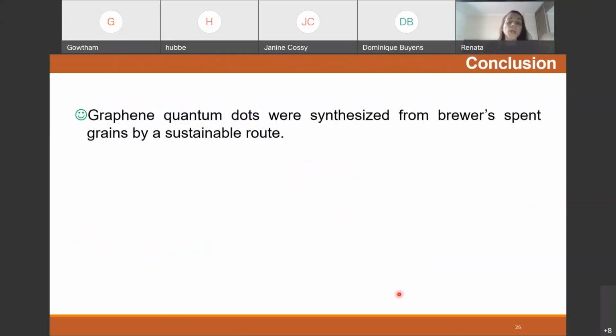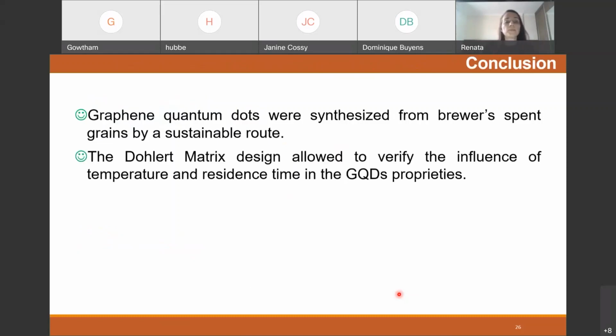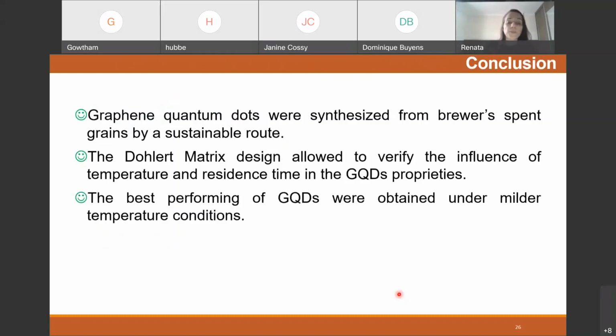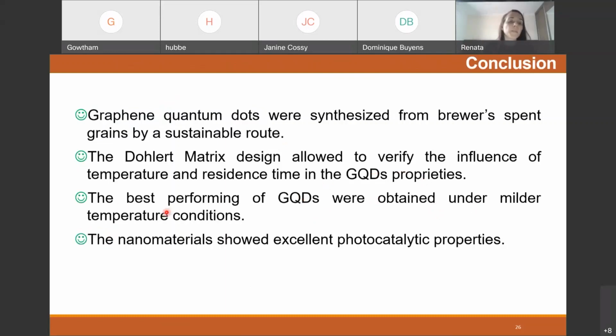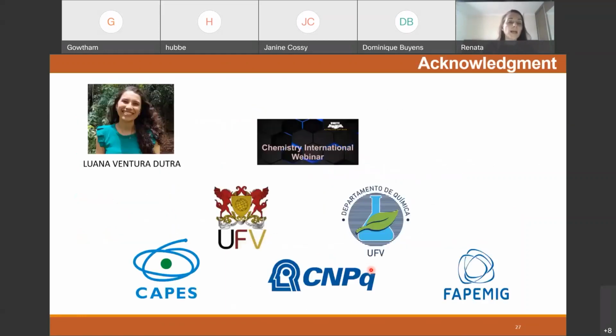molecule. Then it can be concluded that graphene quantum dots were synthesized from brewer's spent grains by a sustainable route, and the Doehlert matrix design allowed us to verify the influence of temperature and residence time on the graphene quantum dots' properties. The best performance of the graphene quantum dots was obtained under mild temperature conditions, and the nanomaterials showed excellent photocatalytic properties.